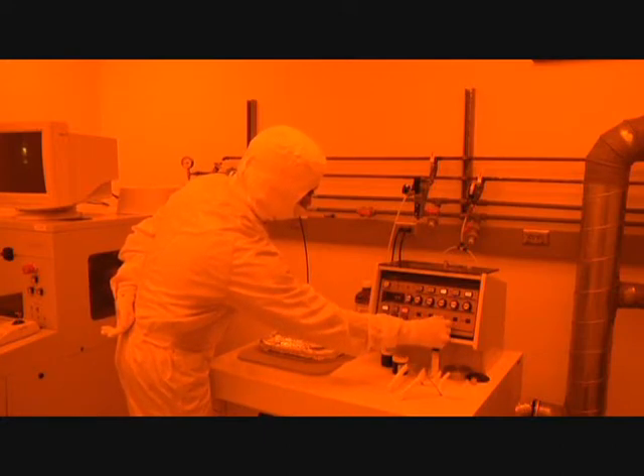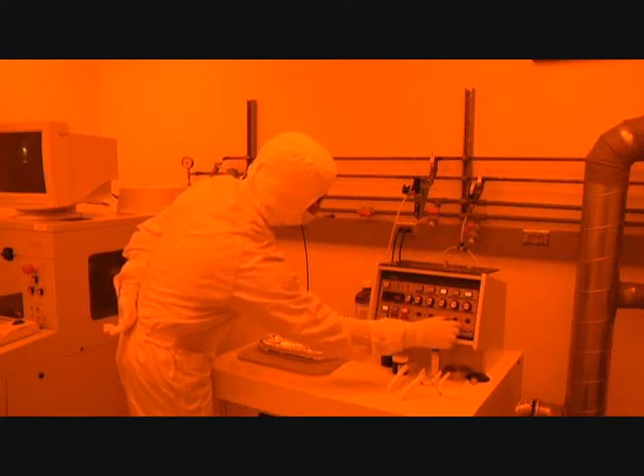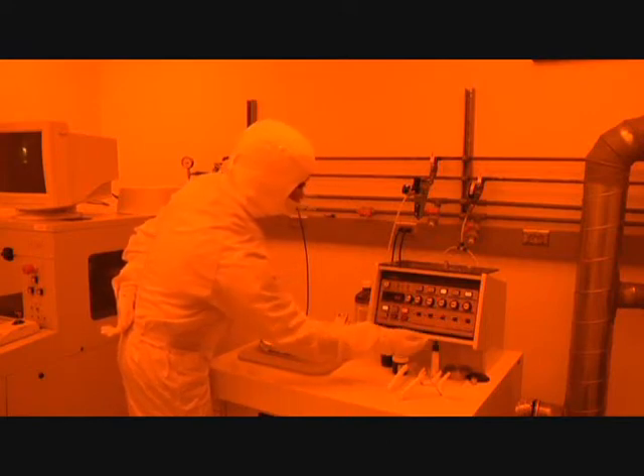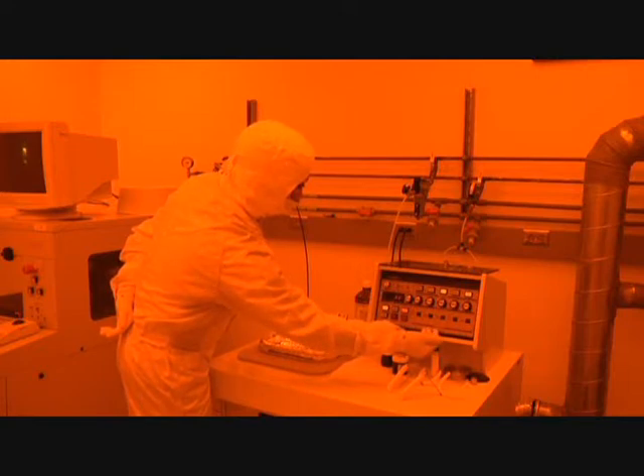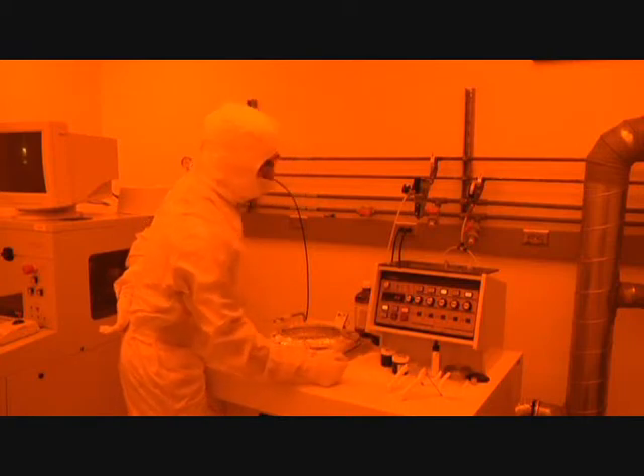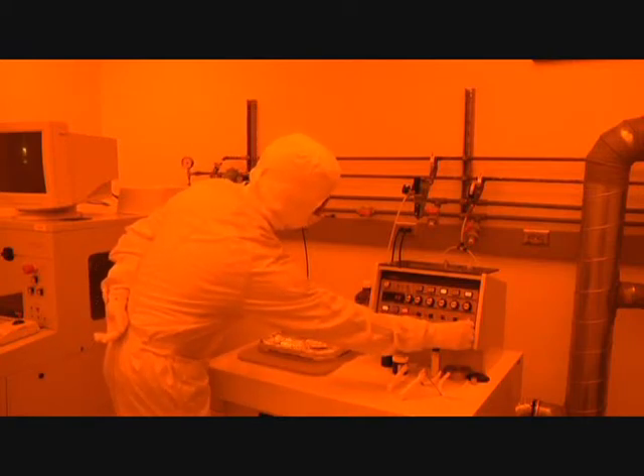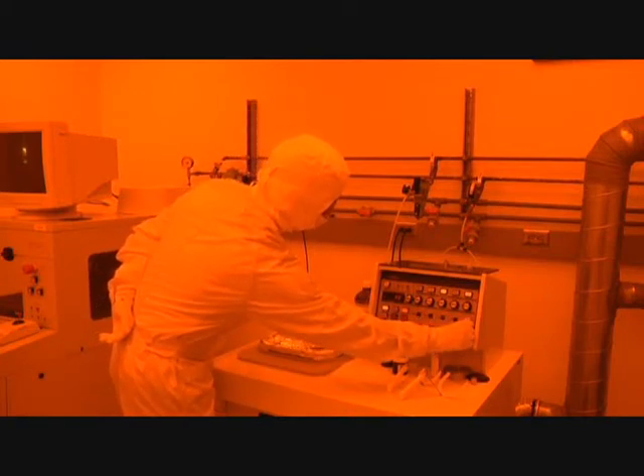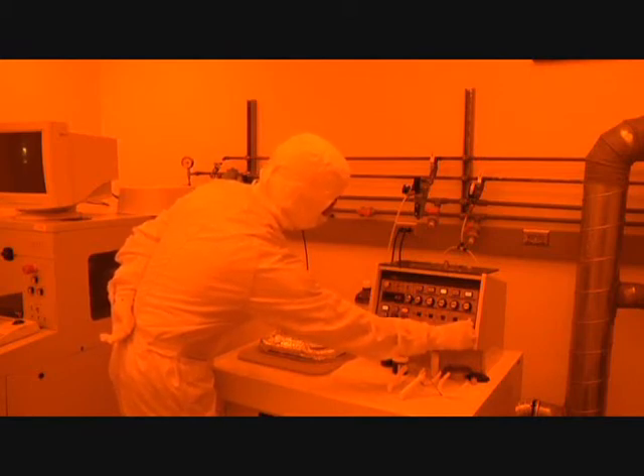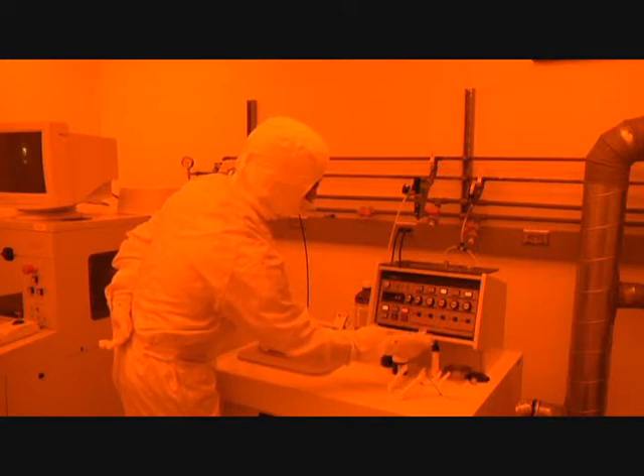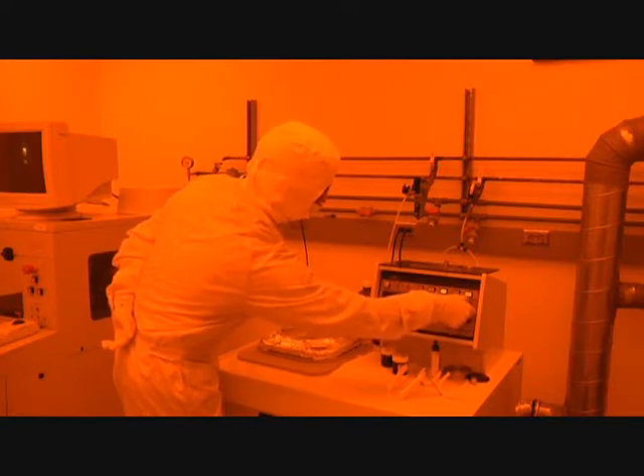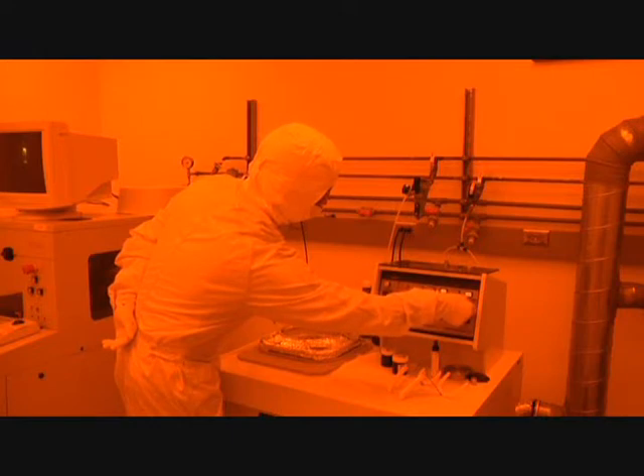What we're going to be spinning is 1818 photoresist. The spin that we use is a 3-second spread at 400 RPM and a 30-second spin at 2500 RPM. So it'll do the slow speed spread first to spread the photoresist out on the wafer, and then it will speed up to cast a nice uniform film of photoresist. The first thing you want to do is make sure you have those spin parameters set correctly.